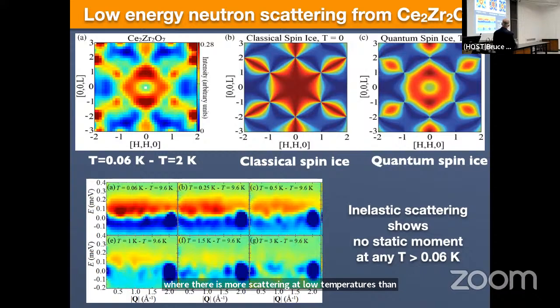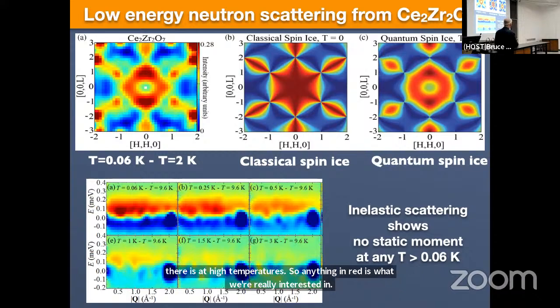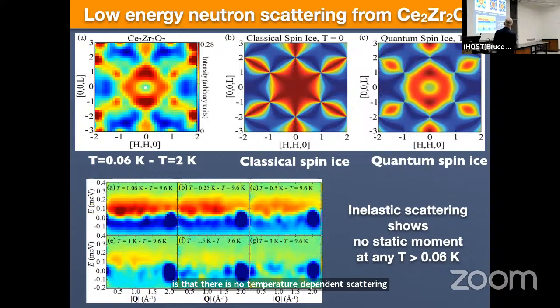And you can see that by the time you get to 3 Kelvin, there really isn't anything left. Okay, but as you go down below 1 Kelvin, you get this red region, which exists between 0 energy transfer and about 0.25 meV. So one conclusion that we would have right away is that there is no temperature-dependent scattering at the elastic position at 0 energy transfer, which tells us that there's no static moment on the timescale of the neutron scattering measurement for any temperature above 60 millikelvin. And it also tells us that what's going on in this material is going on in this range of energy.